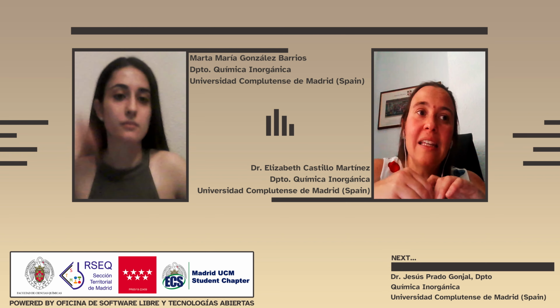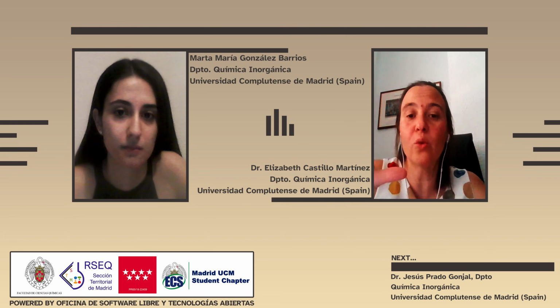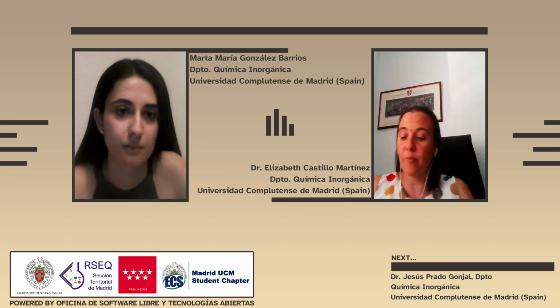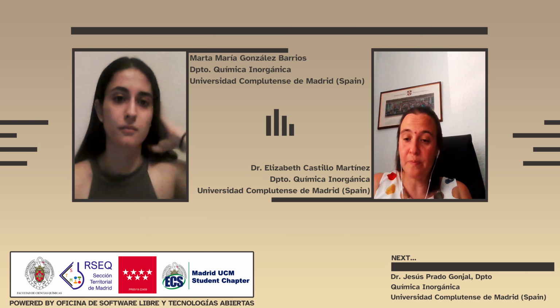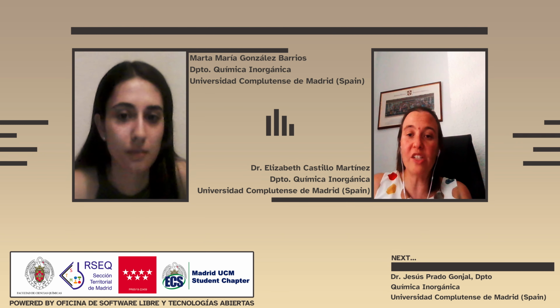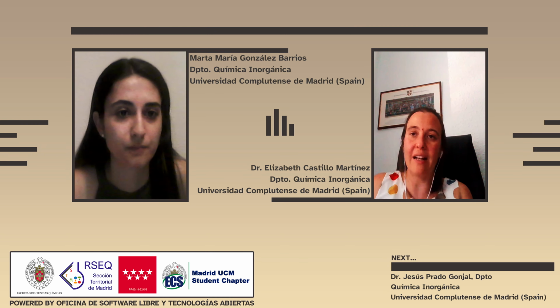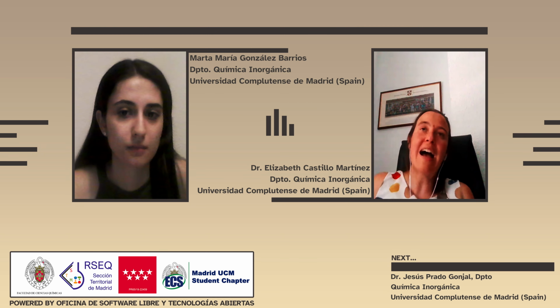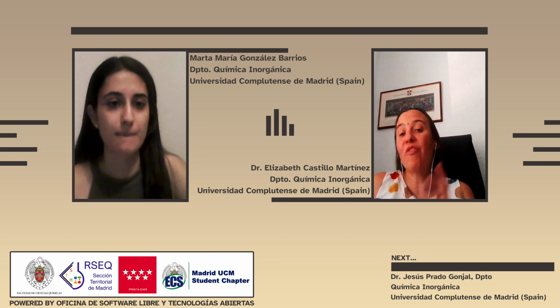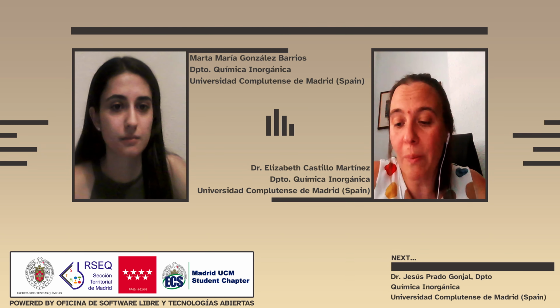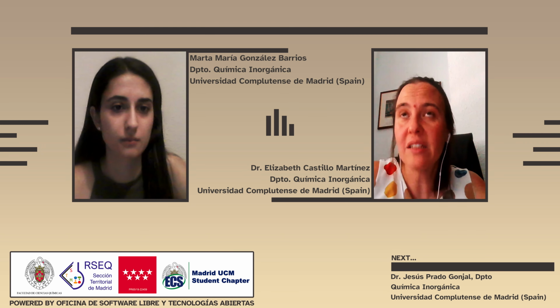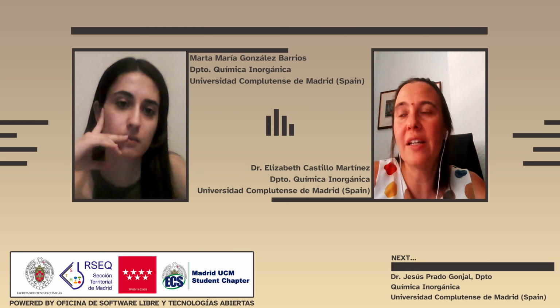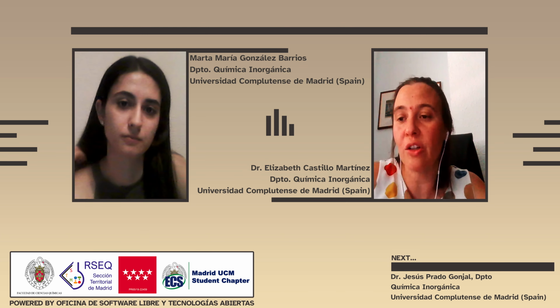So what typically you can do is just do the measurements in a 2-electrode configuration using the sodium or potassium metal as your counter and reference. If you want more precise control of the voltage, do measurements in a 3-electrode configuration where you use sodium or potassium metal as a counter electrode, where you build up a very large SEI layer because there is a lot of electrolyte decomposition, and then use sodium or potassium metal as a reference electrode. But still, this is going to have some contribution from the electrolyte decomposition surface.